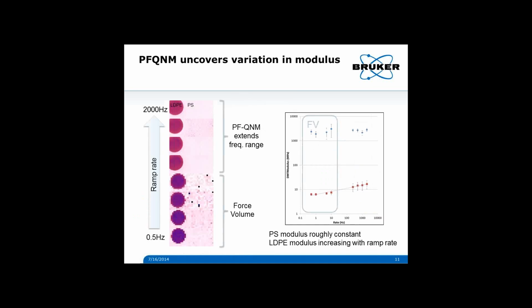So what I've done is I went ahead and I did some measurements using both force volume, which allows me, as I mentioned earlier, to do lower ramp rates, and peak force QNM. And so I started out at 0.5 hertz with force volume images, and these are all individual images. So we have 8 images here, 4 in force volume. And you can see I used a lower pixel count so that I was able to have this take a reasonable amount of time. And I increased the ramp rate up to 2 kilohertz with peak force QNM. And you can see that the color of the polystyrene part, this kind of light pink area, is roughly the same for all of the curves.